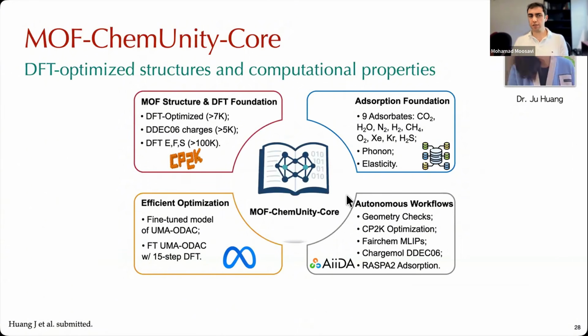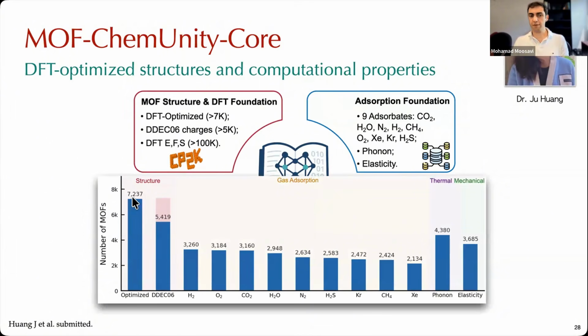So that's what Ju implemented as the MOF-ChemUnity-Core study, which is DFT optimization of structures in the CoRE MOF database, and then further computing all sorts of adsorption properties. It has about 7,200 DFT optimized structures, 5,000 partial charge calculations, gas adsorption for all sorts of gases, and also computed mechanical and thermal properties. These are just data that we collected and added to the MOF-ChemUnity as an environment for storing computational and experimental data for MOFs.